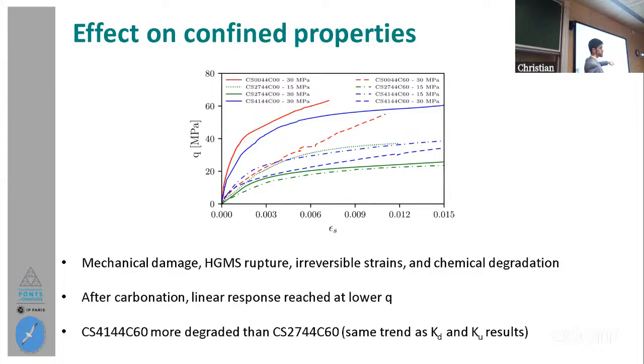Okay. So the dashed line corresponds to the cement paste. The solid one corresponds to CS2744 C00 with 30 megapascals of confining pressure. And then the dotted corresponds to the same cement paste but with 15 megapascals. And maybe that's what you're referring to, right? Yeah. Yes, what I did mention there is that there is some influence on this difference in the behavior between this one and this one due to the rupture of the spheres, which is actual mechanical damage that is occurring. So I was referring to that. Maybe I was not clear in the manuscript. But this was to start my question. Okay, yeah, perfect. Sorry.